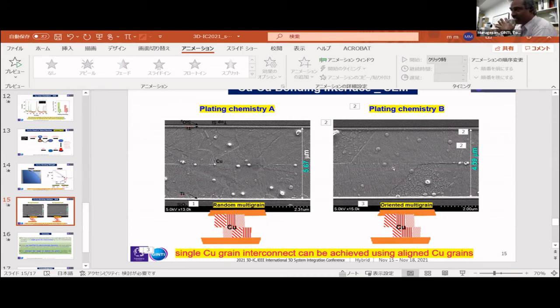This kind of single grain is very, very important when you move on to less than a micron size, your copper micro joint or other things. We have to have a single grain to reduce your joint resistance. So we were finally able to achieve these kinds of things using our modified electroplating chemistry.